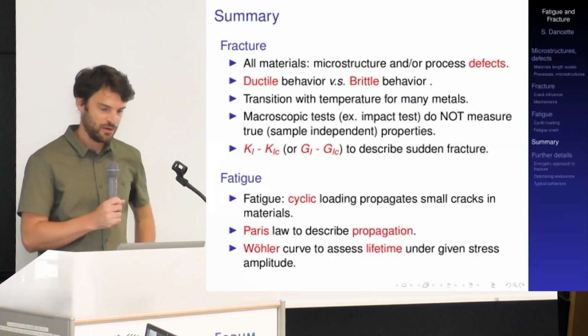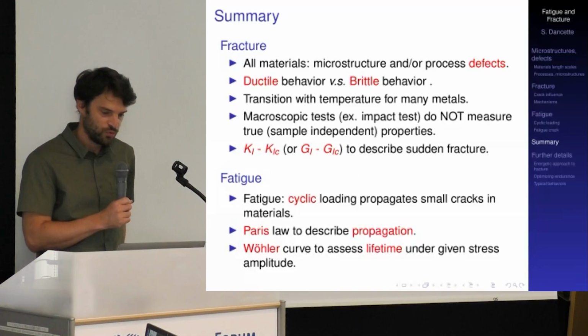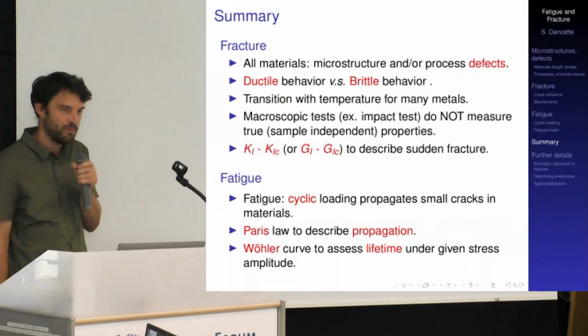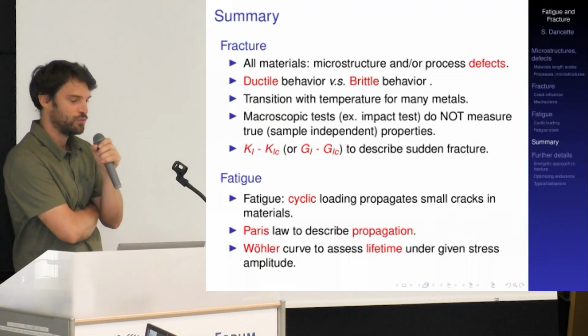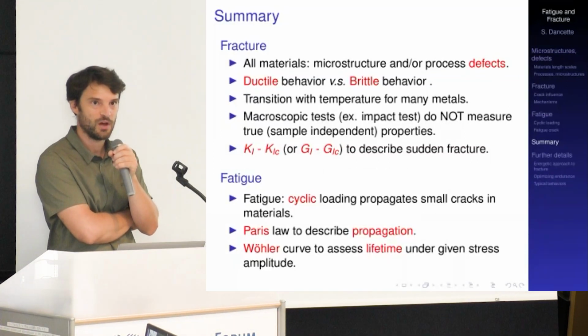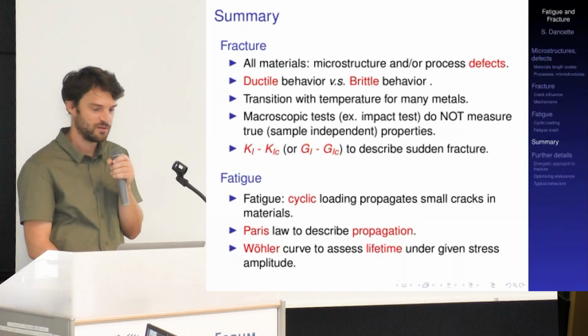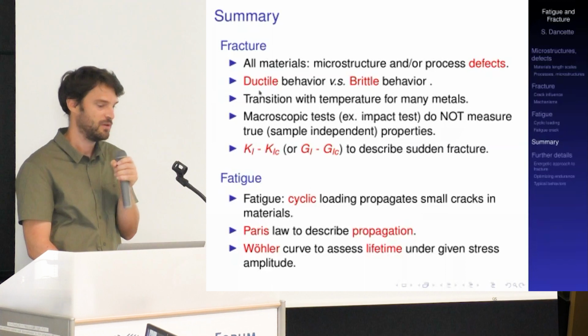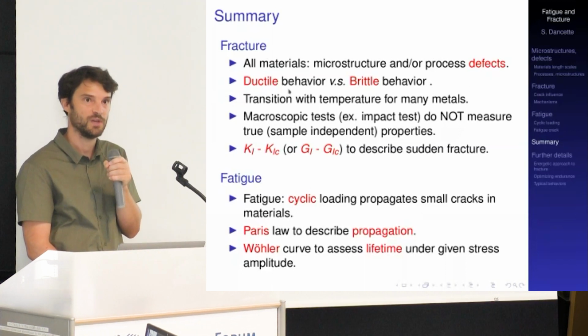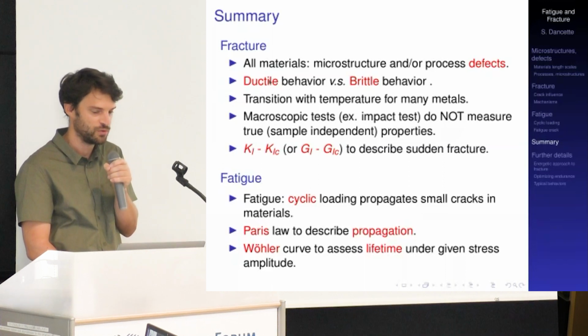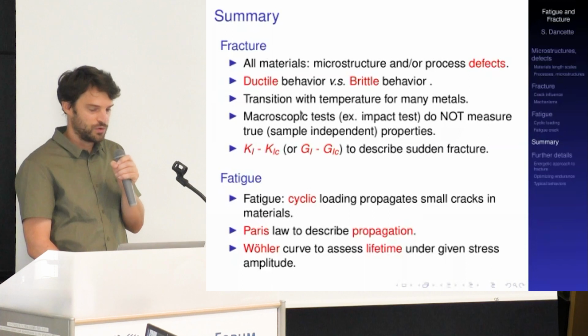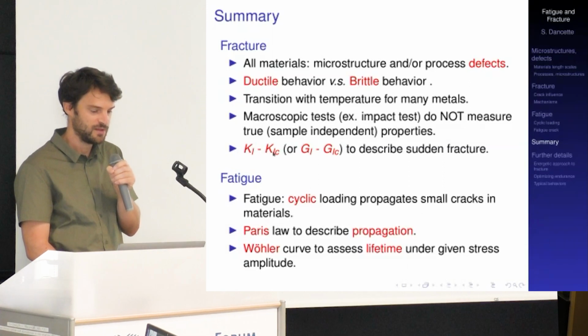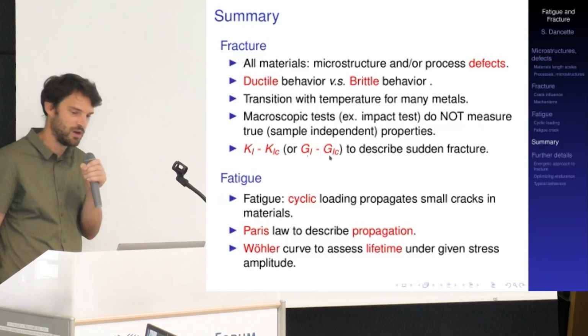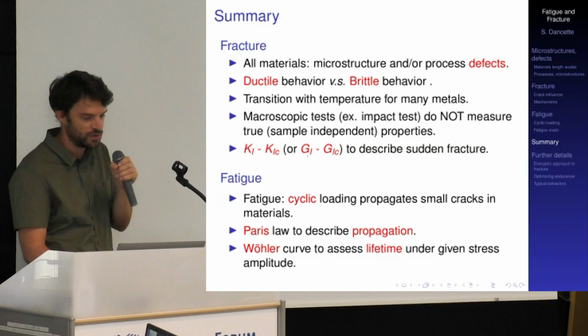So with this, I have to conclude. I tried to show you today that all materials, all classes of materials, depending on how they were produced, usually contain defects. Defects may be small, may be large, depending on the way the material was produced. And what makes a difference between materials is the way they behave in the presence of such defects when loaded mechanically in tension or in compression, so when loaded in service conditions. So we had to distinguish between ductile behavior and brittle behavior. And we also said that one of the most important properties for describing fracture is the fracture toughness, K1C, or its dual analog, G1c, the fracture energy or toughness.